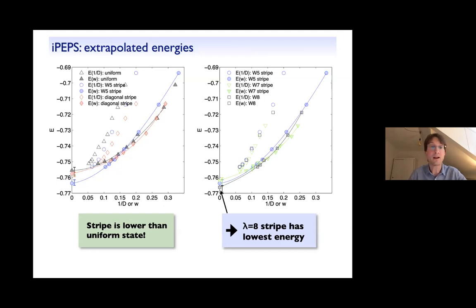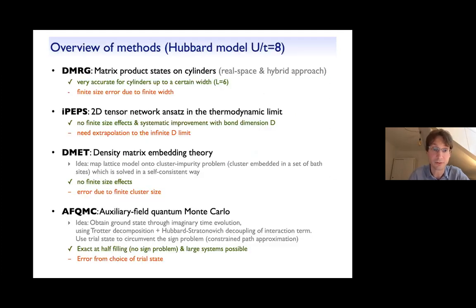Okay, so let me now also show you the comparison with the other approaches used by my collaborators. Before showing you the data, here's a one slide summary of these approaches with their main advantages and disadvantages. I will not go into the details, just very quickly. In DMRG, you can get very accurate results for cylinders up to a certain width, and for the 2D Hubbard model, that was up to width 6. But you have a finite size error due to this finite width. Then iPEPS, as we have heard, has no finite size effects, but you have to rely on an extrapolation to the infinite D limit. And then another approach is DMET, density matrix embedding theory, where the idea is to map the lattice model onto a cluster impurity problem, which is then solved in a self-consistent way.